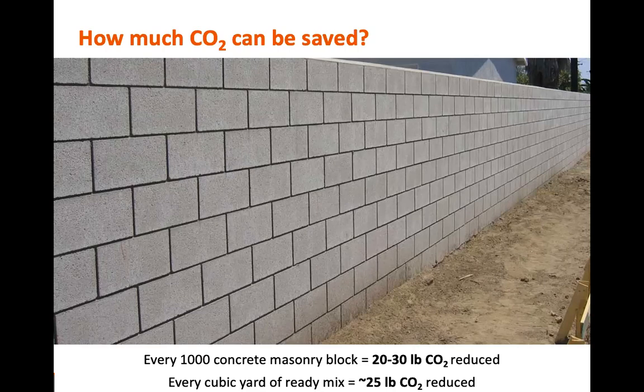Because it's forming that calcium carbonate material, you generally don't see many other impacts to the features of concrete we care about. No real issues with workability, freeze-thaw, pH, or density. You can color concrete the same way and do all the things you normally do with it — the only difference is that it has a little more calcium carbonate inside it. For masonry blocks, you could get about 20 to 30 pounds of CO2 removed and stored in the block itself for every thousand blocks. For a cubic yard of ready-mix concrete, you would see about 25 pounds of CO2 reduced. Precast would also be roughly around the same.